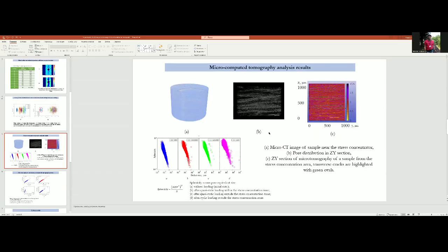And our analysis with the Bayesian-Gaussian mixture models shows that loading creates separate groups of small and large pores. We found that cyclic loading doesn't change pore orientation, but it radically reorganizes them. It destroys the natural pore clusters found in untested samples through expansion and merging. This reorganization process causes the strength reduction. These findings are a key step toward better prediction of composite failure.